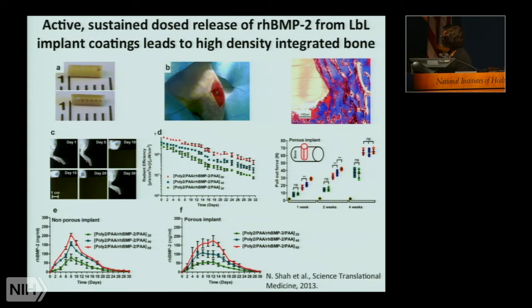But the pull-out forces that we see with these different doses indicated by different numbers show that in the first couple of weeks there's a dose dependence and a very strong increase in the pull-out force. But by the time we reach 4 weeks, everything has leveled off. And we see that even our lowest dose system is able to provide a very highly integrated implant bone material interface. And in fact, the strength of this pull-out force is about 4 times that is generated with polymethyl methacrylate bone cement, which is commonly used. We can also note that when we pull these out, at this point, we see that the fracture takes place in the bone, the native bone, and not at the bone material interface.